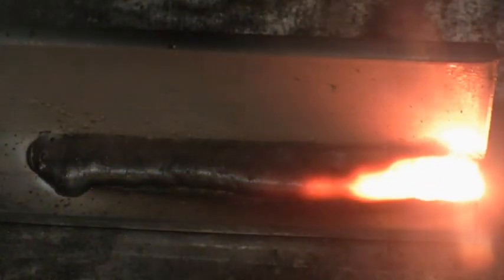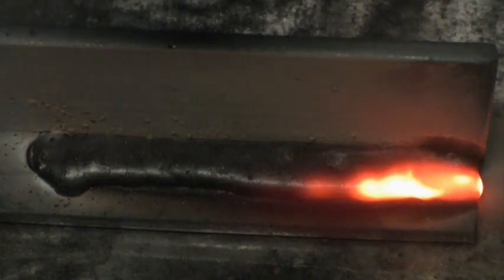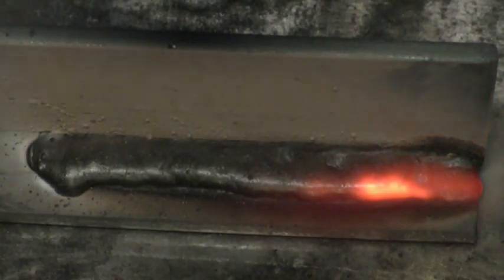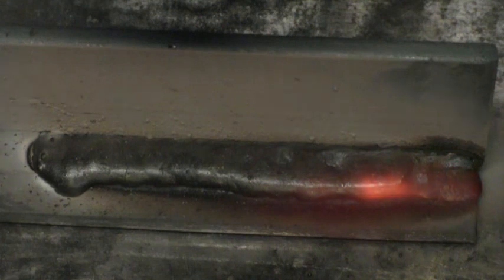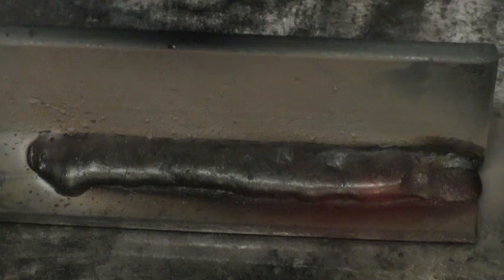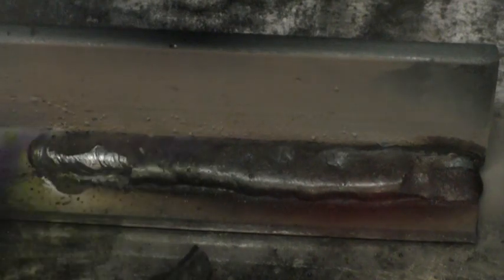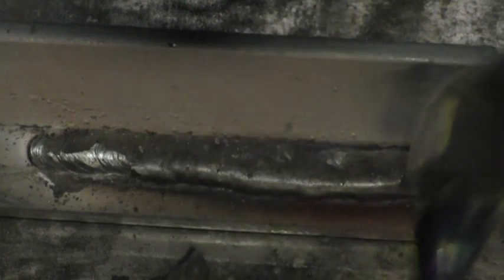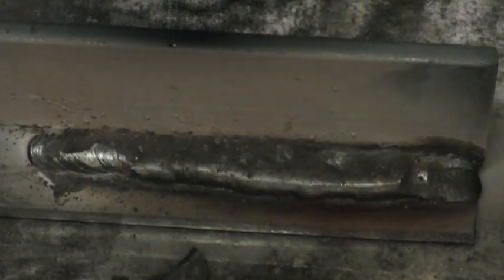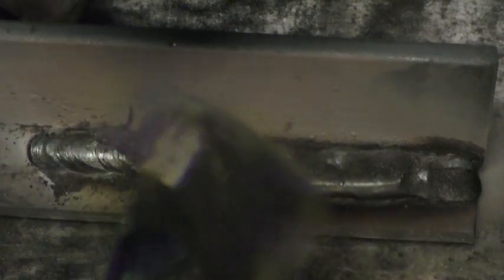and take a look at the puddle, the back edge of the puddle. When the arc is at its correct length, you can see the slag. I can feel the rod touching the plate. It's thicker and darker in color. It may not necessarily show up 100% on camera, but you should be looking at that oval shape, liquid. On verticals, you won't necessarily feel it while you're welding, unless you're weaving a little left and right. Overhead, you may not feel it at all. But you should occasionally feel it bumping your plate when it's at its correct arc length.